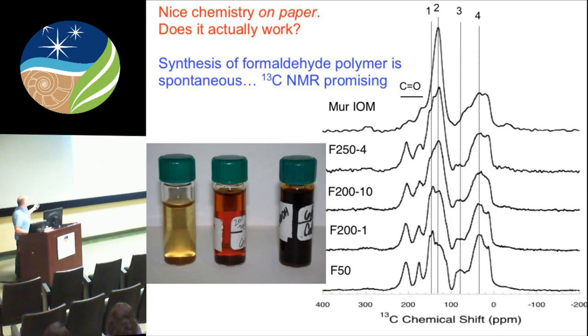What we did was, it's nice chemistry on paper, but does it actually work? So we basically did the experiment in the laboratory. We started out with a moderately basic solution of formaldehyde with a little bit of glycolaldehyde. And instantaneously, it turns strongly colored, black particles start to sediment out, eventually it's completely opaque, and the bottom is filled with some black stuff. So we take off the solution, we dry down the black material, we do C13 NMR. If we do this experiment at 50 degrees, and this is the NMR spectrum of Murchison, you see the same types of functional groups represented.